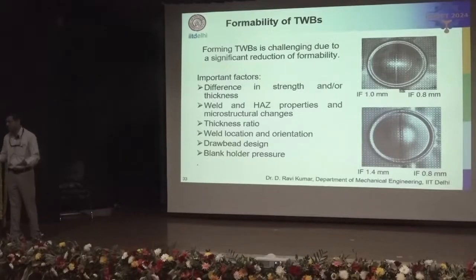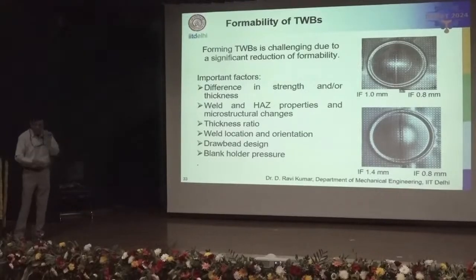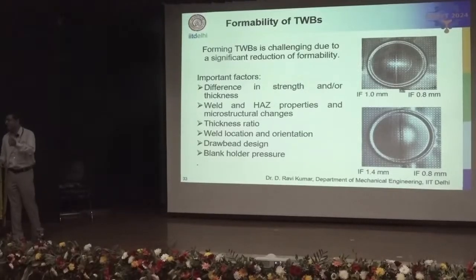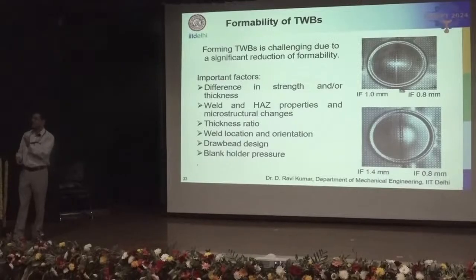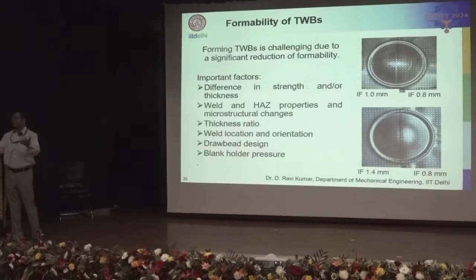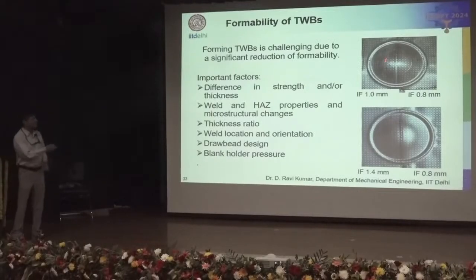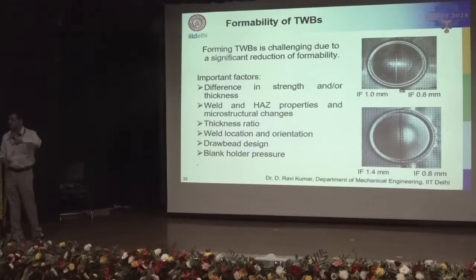So the material behavior changes because the properties are different. And the weld region itself behaves in a different way, because usually the weld region has lower ductility when compared to the parent sheets. And in addition to that, you have a small heat affected zone. So it is important to consider all these things when we design the tooling and the process variables when we form the tailor welded blanks.